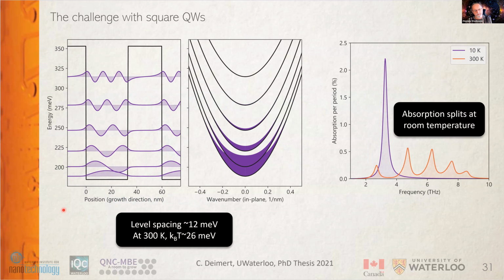Now, people were trying to do that and demonstrated some polaritons at low temperatures in square quantum wells. However, the problem with the square quantum wells is that you cannot bring them up to room temperature. The levels are not equally spaced. You start to populate all of them, and you end up with washing out your entire oscillator strength and transition from one sharp line, which is needed for polariton at low temperature, into many lines and many transitions, and in fact everything broadens and is no good. So takeaway message from this one: square quantum wells will do the polaritons, but only at low temperature. So we need to go into something else,